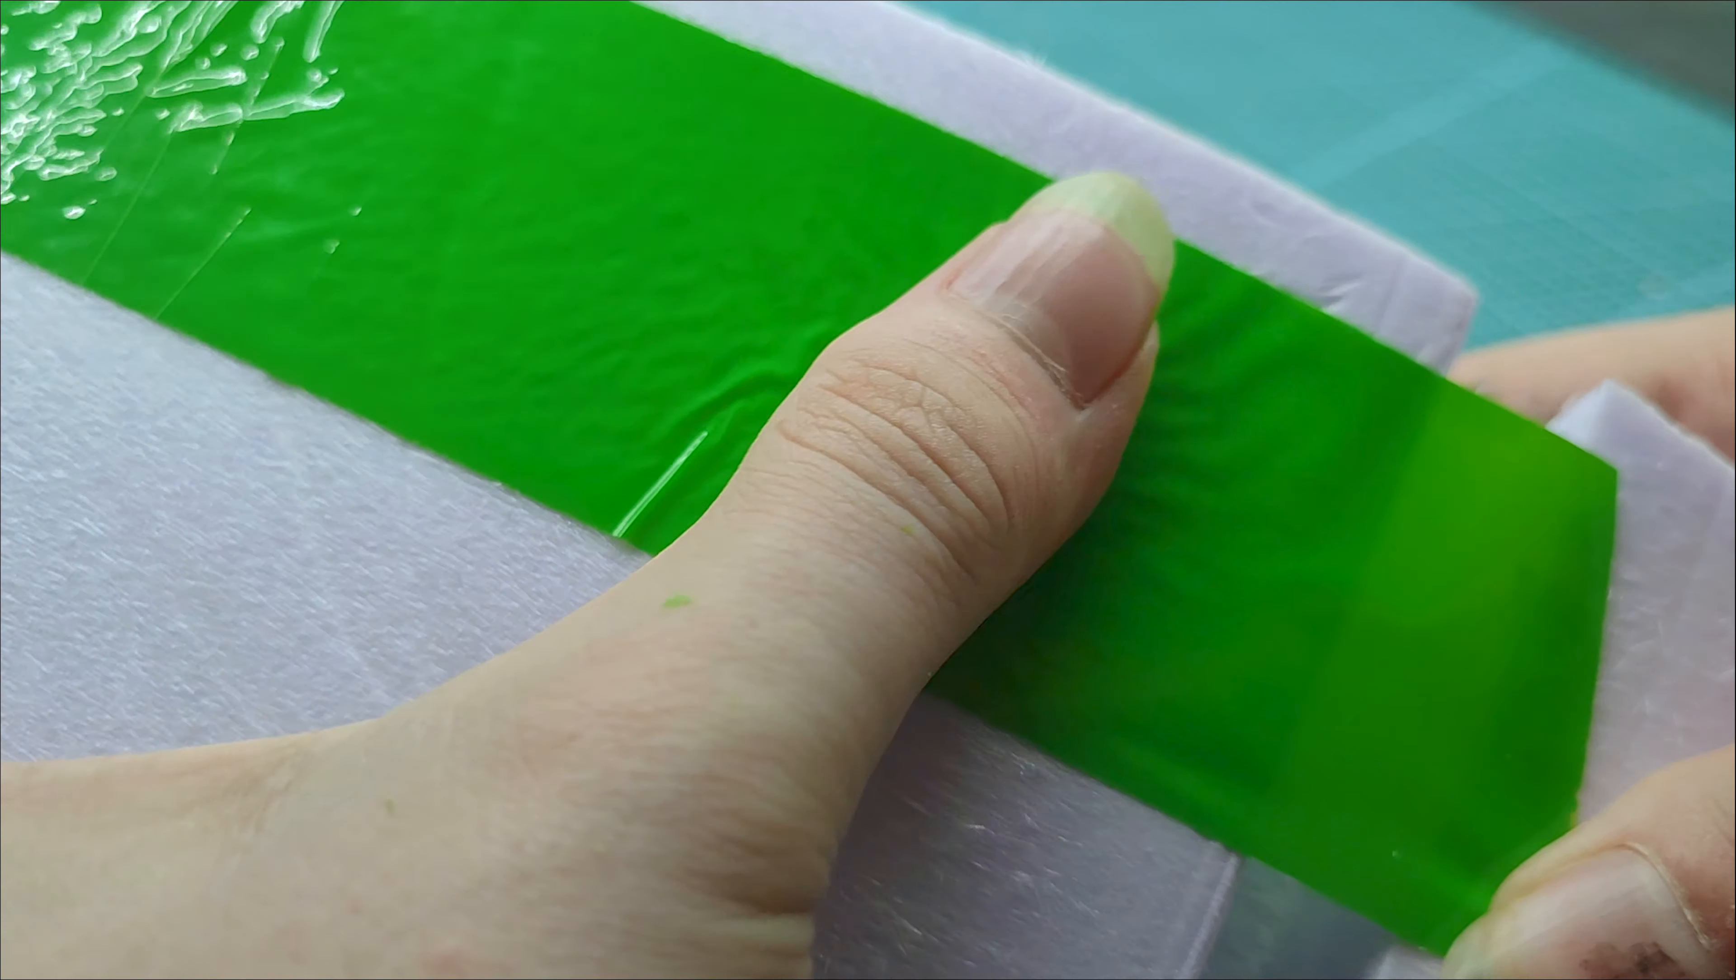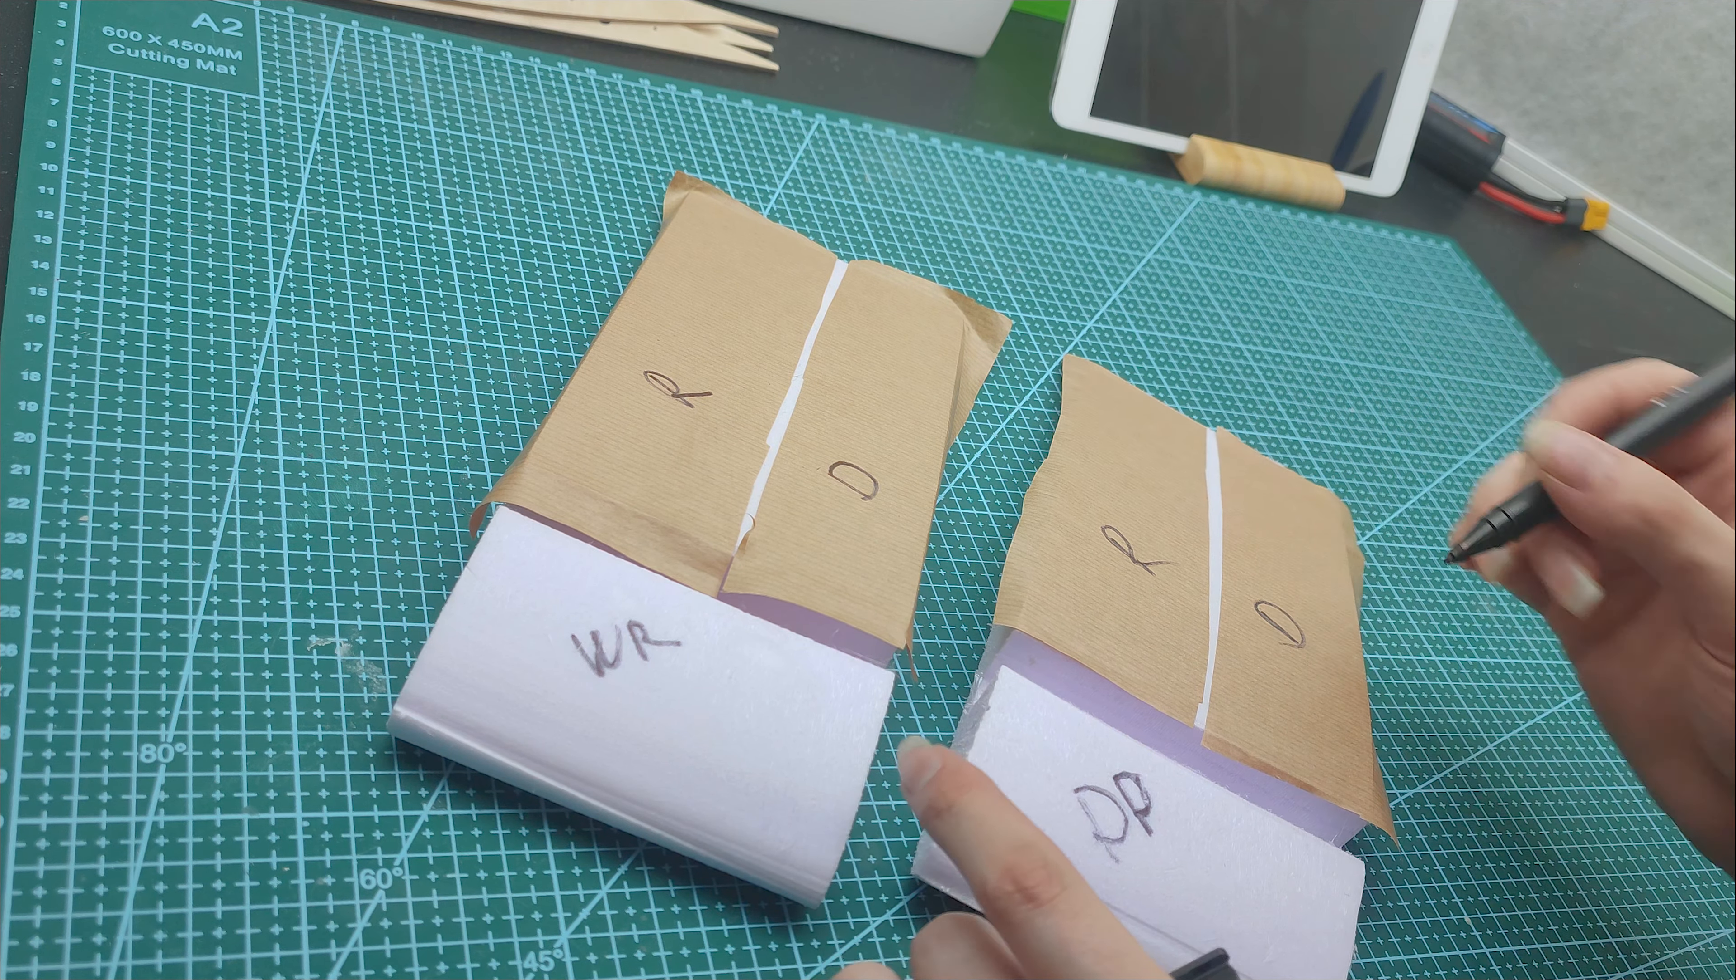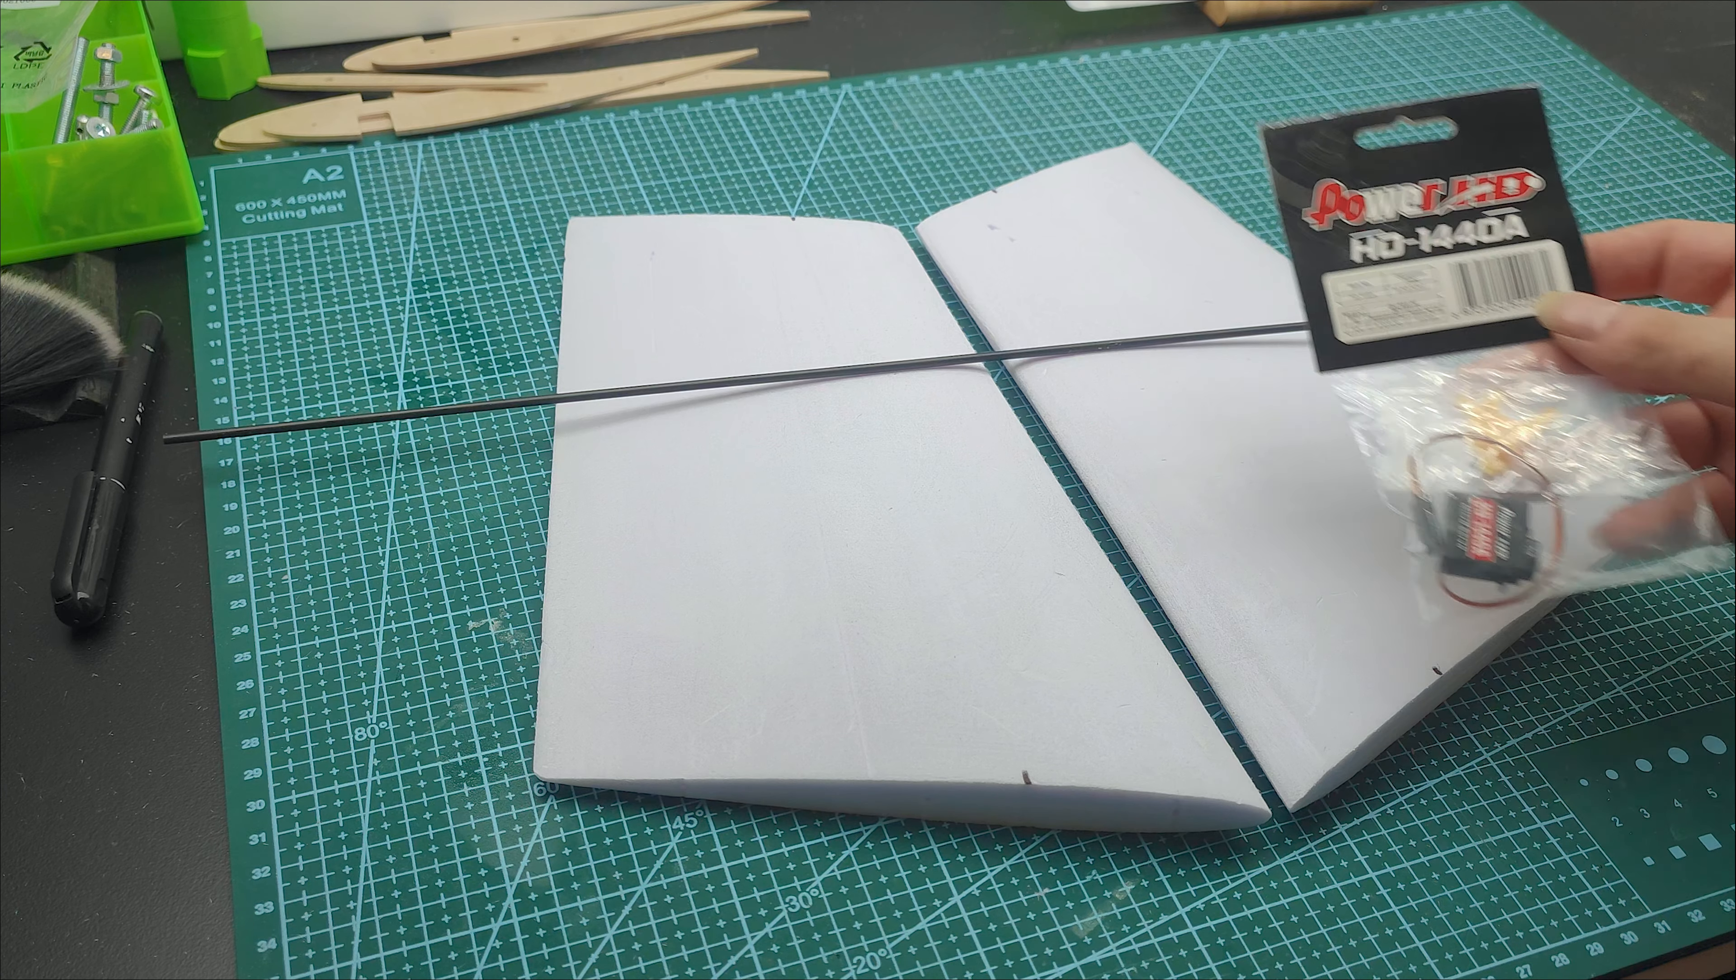Now we need to coat the wing. My initial plan was to use color tapes, but as I tested the adhesion, it was really unacceptable. It holds very well on the iron, but not on the XPS foam. So what to do now? I want nice and smooth finish. So I went the foam board style. On test pieces, I tried to glue light brown packing paper with PVA glue in combinations of wet or dry paper and raw or diluted glue. And any option holds on the foam better than on actual foam board. The best result was wet paper and raw glue, but it's extra weight, so instead just a little diluted glue. Now it's gonna be good for tape or spray paint.